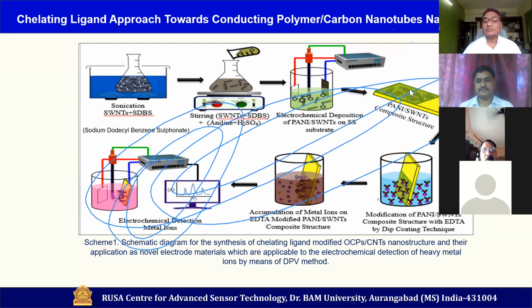Once we have the composite on the substrate, then you can do modification of that with various chelating ligands, because we are using chelating ligands for enhancement of the selectivity as well, right? Selectivity as well as sensitivity. So by dip coating, we are modifying the composite structure with chelating ligand. And then for differential pulse voltammetry, for stripping, first of all, we need to accumulate the metal ions. Accumulation is being done by dipping the substrate in the solution of given metal ions, and then we are doing electrochemical detection. So this is the protocol for development of the sensor strip and detection of metal ion in the laboratory.